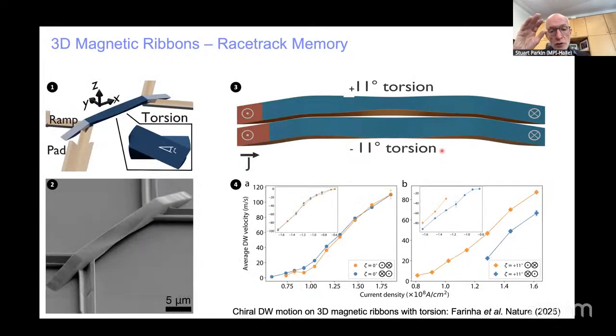And then here we've used this to grow magnetic ribbons. And this is a result from a paper we published early this year in Nature, where we demonstrated for the first time a truly three-dimensional racetrack. And in this picture on the left, bottom left, you can see essentially like a bridge we formed from the racetrack with a twist, a geometrical twist. And on the top of this geometrical surface, we build a racetrack which has this chirality introduced, as I already mentioned, by this Dzyaloshinskii-Moriya exchange interaction.